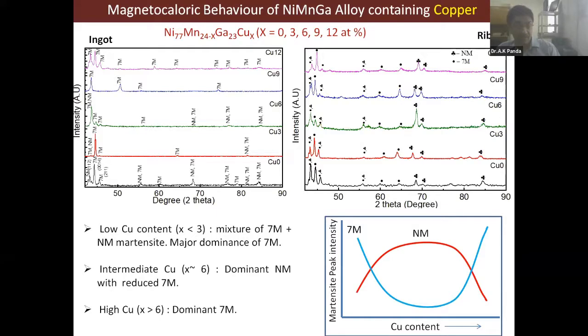Now this is just to tell you, I run fast, because this is a modification of nickel manganese gallium with a copper addition. What you find is that it is typically a combination of different modulated and non-modulated martensites. When we have a low copper content, less than 3%, we have a combination of modulated and non-modulated martensite, wherein we have a dominance of 7M modulated martensite and so on. Schematically, I try to show you in the bottom right how the non-modulations and modulations change with the copper content. With increasing copper content in the alloy, at an intermediate copper content you can have a dominant non-modulated martensite and reduce the modulated concentrations, whereas at a very high copper content, you can increase the modulated martensite content.